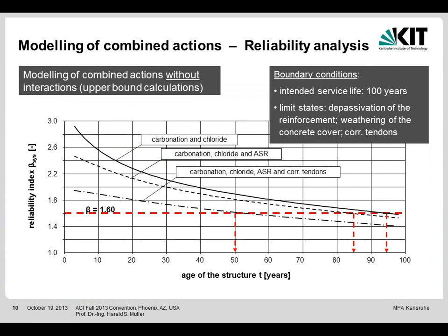You see here the boundary condition, intended service life 100 years, and different limit states due to different actions: the depassivation of the reinforcement, weathering of the concrete cover, and corrosion of tendons. You have here the decreasing reliability for carbonation and chloride. You end up at 95 years. Planned has been 100 years. If you have, in addition, an alkali silica reaction with a certain probability, you see you end up already at 85 years. And if you also have corroding tendons, then the curve is much lower.